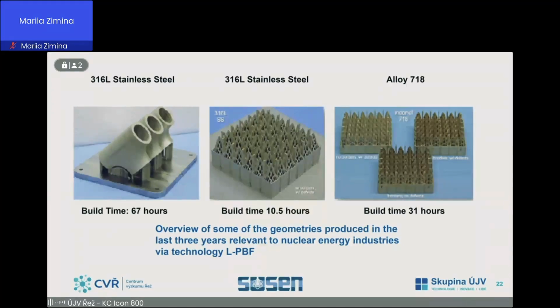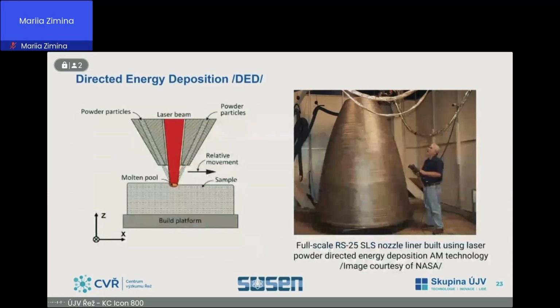Another additive technology is directed energy deposition, which is an additive manufacturing process in which concentrated thermal energy is directed to melt deposited materials. The process consists of depositing individual layers of powder produced by gas atomization process with thickness of approximately 0.25 millimeters.